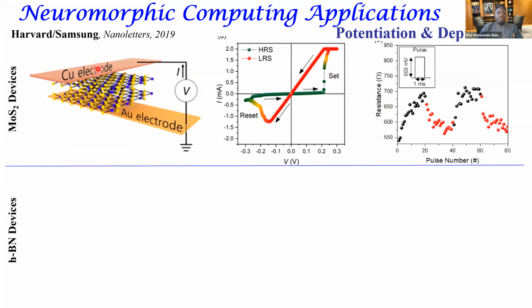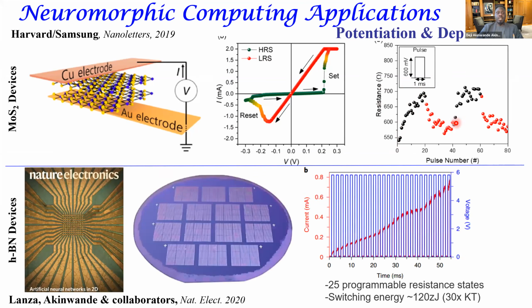They use copper in this case instead of a symmetric structure, because copper, they claim, is lower energy. So switching voltages are just not far from thermal energy, about 0.2 volts. And they could program the resistance states. I won't talk too much about this, but you want to be able to program the resistance states increasingly - that's called potentiation. You want to be able to program them also in a decreasing slope - that's called depression. These characteristics are critical for neuromorphic applications.